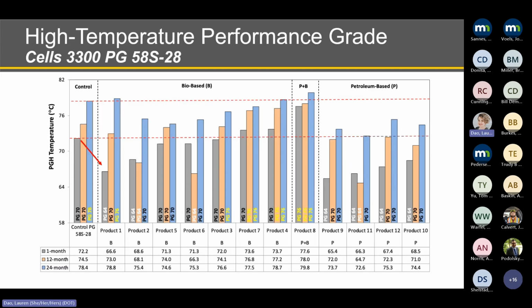So the first set of data presented here is related to the surface with a neat binder, PG58S-28. And here you can see the pass/fail temperature at the high end of the performance rating. You will see it divided into control, bio-based products, the hybrid product, and the petroleum-based products. And we have results after 1 month, 12, and 24 months of treatment being applied. For each category of products, we have the data organized from the lowest pass/fail temperature to the highest, considering the 1 month field age interval.